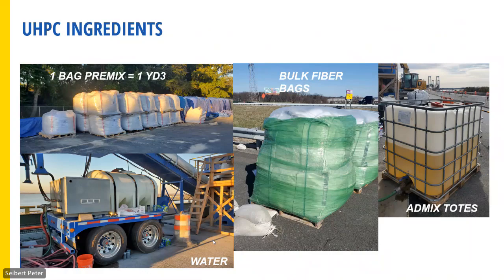So UHPC typically comes pre-mixed like Peter had in the little vial that you guys saw before. It'll come with the dry pre-mix, which has the sand, cement, and any other proprietary cementitious dry admixture. That's all in this bag. Comes from a blender into the bag, comes wrapped up and shipped out to your job site. So on this project, we elected 1 cubic yard super sacks. You can get them in different sizes, but that's what we used here. And you could just imagine that was a lot of room to have thousands of super sacks stored on site to be ready to mix on site. The fiber typically comes in 40-pound bags, but for this project, we moved up to a super sack of steel fibers.